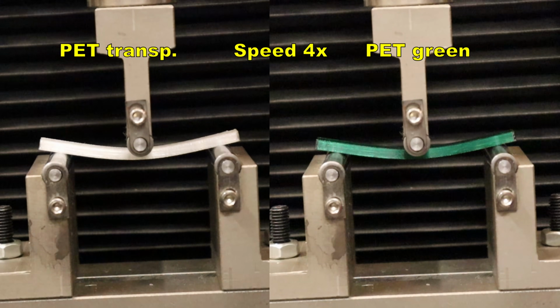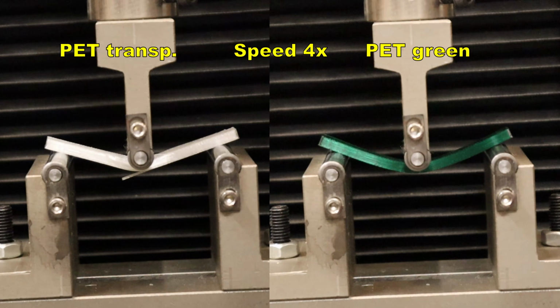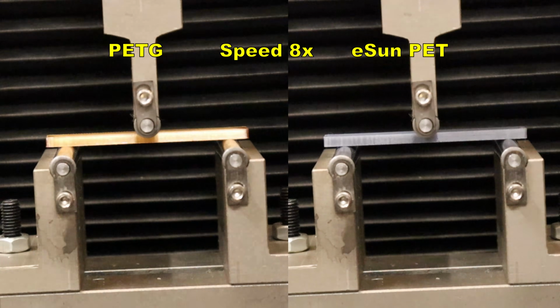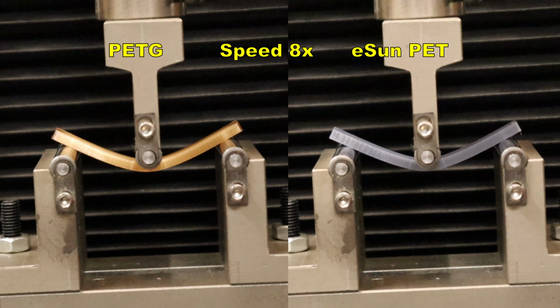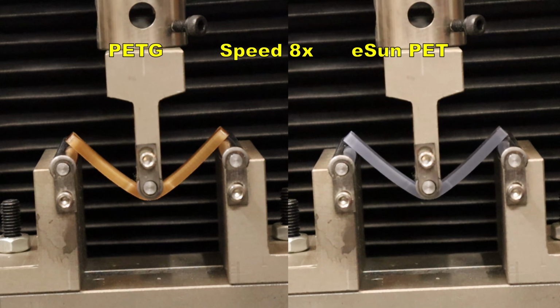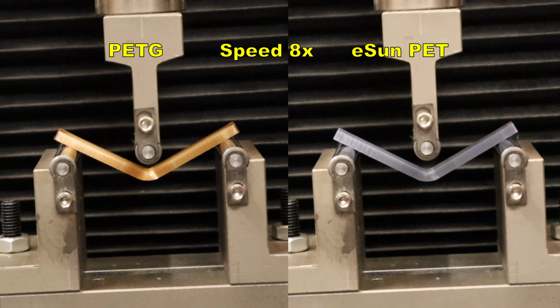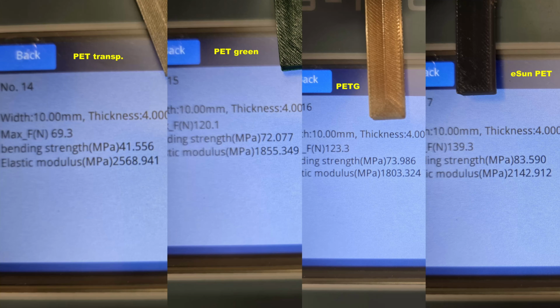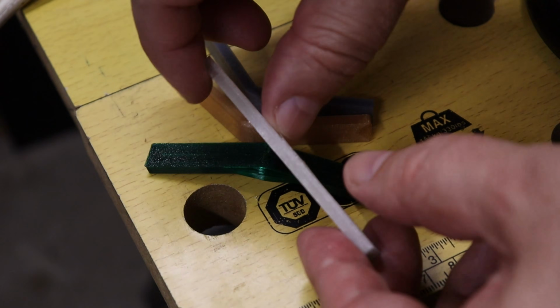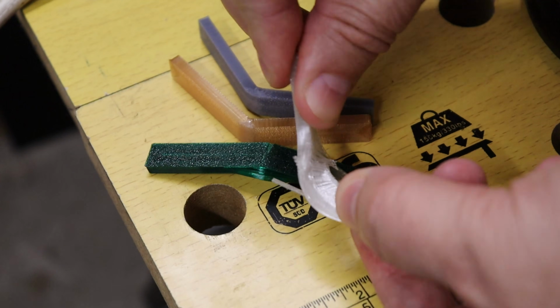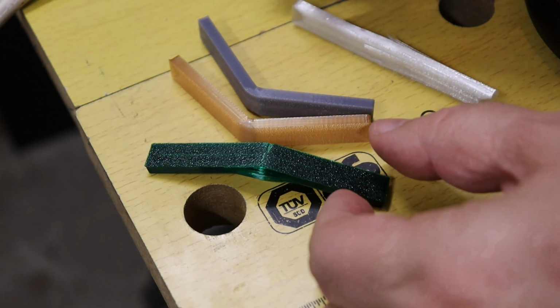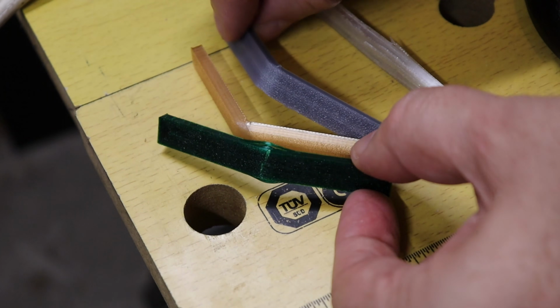3-point bending test. These are recycled PET filaments, translucent PETG and eSun PET, sped up 8 times. Max load, bending strength and elastic modulus, but I will show you everything soon on the graph. And here we can see how weak the layer and wall adhesion is with the recycled PET filaments.